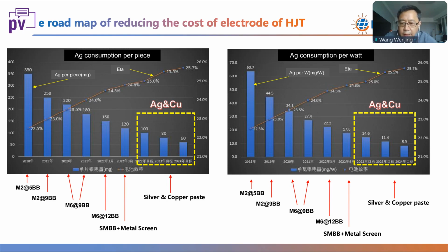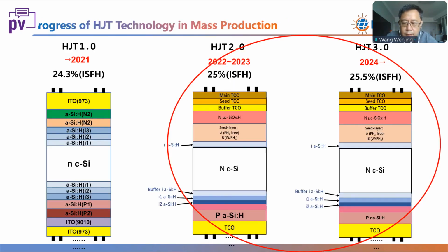Later, as the next step, if we use silver copper paste, maybe we can further reduce the silver consumption to 80 or even 60 milligram per piece. Accordingly, the silver consumption per watt also reduces.